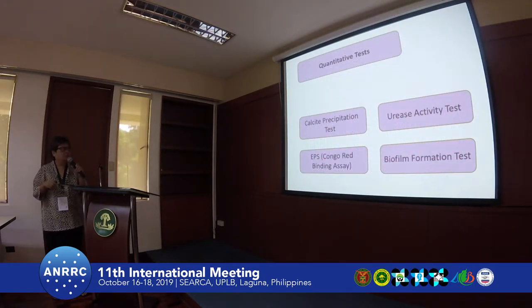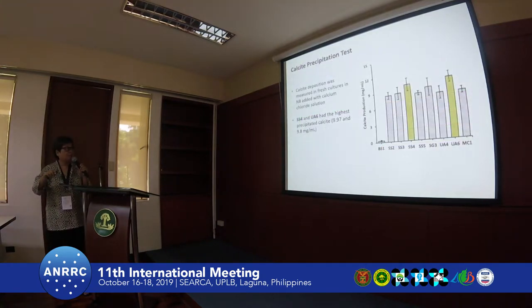So next, we conducted quantitative tests: the calcite precipitation test, the urease activity test, biofilm formation test, and exopolymeric substance binding assay. So these are the properties that we want from our potential isolate. For our calcite precipitation test, we measured calcite deposition when we added calcium chloride to solution, and we found that isolates SS4 and UA6 precipitate the highest amount of calcite.